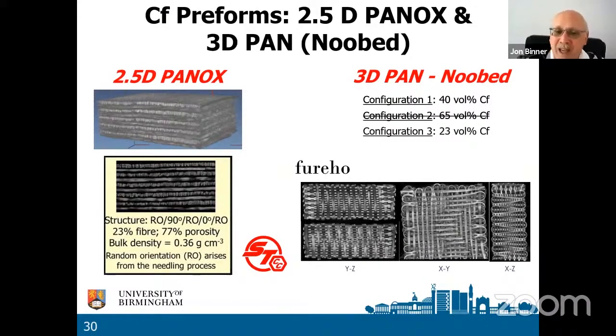And you can see the different weaves, and you can choose anything that you want in terms of the weave. You can have as much or as little fiber in the X, the Y, and the Z direction. So it's a fantastic process. It just isn't cheap. And the 65 volume percent was an absolute disaster. It just didn't allow the gas to flow anything like the required rate. So then we bought some 23 volume percent, and you can understand why 23, because our 2.5D was 23. And so now we're able to compare a 2D and a 2.5D and a 3D, both at 23 volume percent.